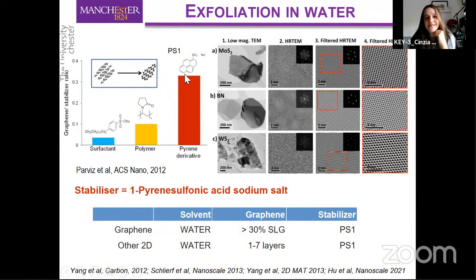And while we were working with exactly this molecule, this paper came out, published by Professor Green, showing a very nice comparison between exfoliation produced with traditional surfactants and polymers and this class of pyrene derivatives. They show very nicely that although pyrene derivatives look like surfactants, the exfoliation is actually much more efficient compared to traditional surfactants and polymers. We can achieve a much higher concentration, which is obviously very important in terms of inkjet printing.